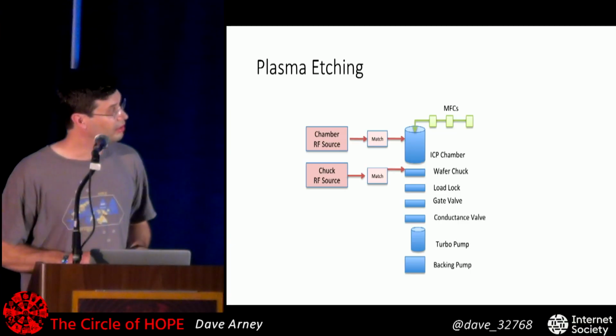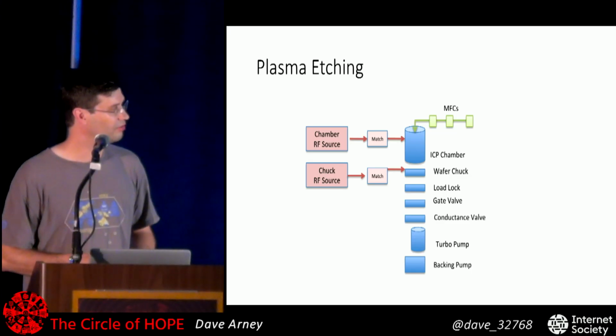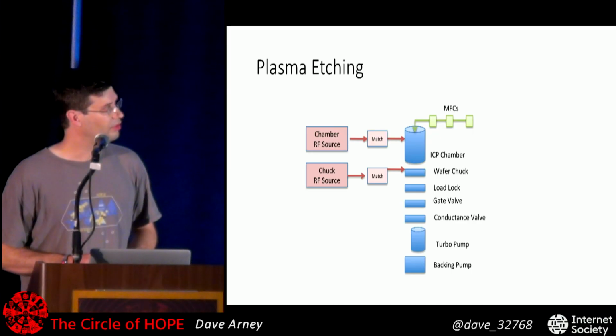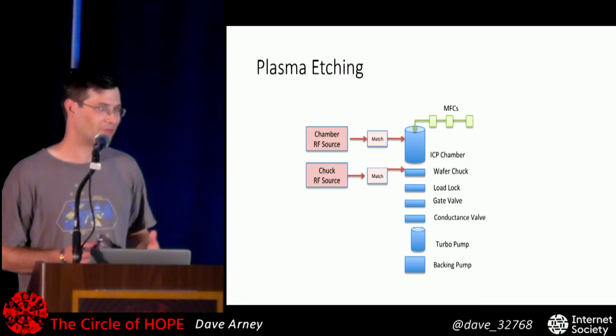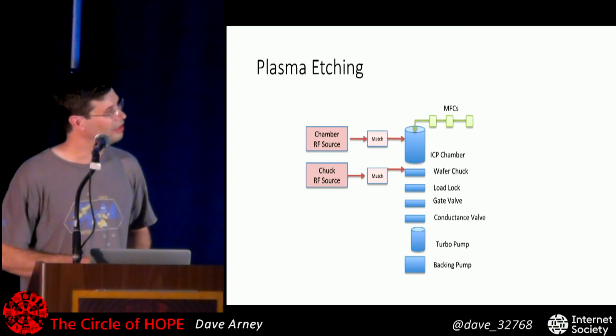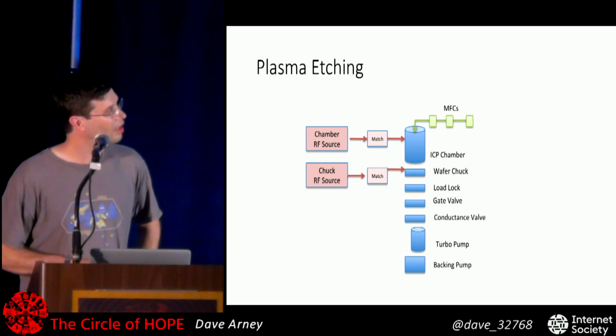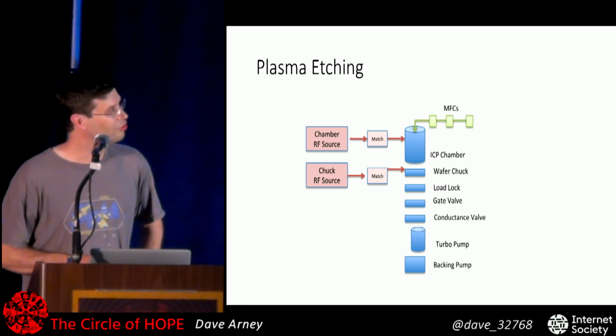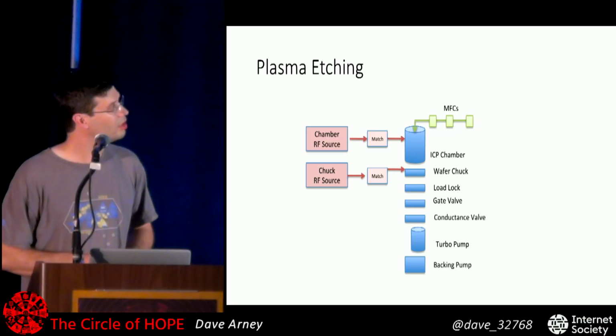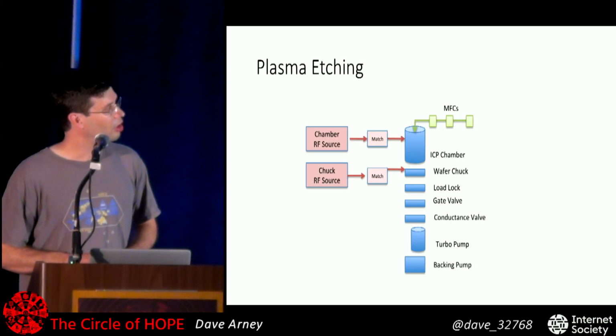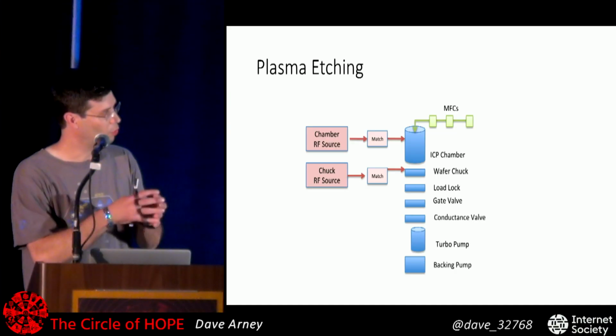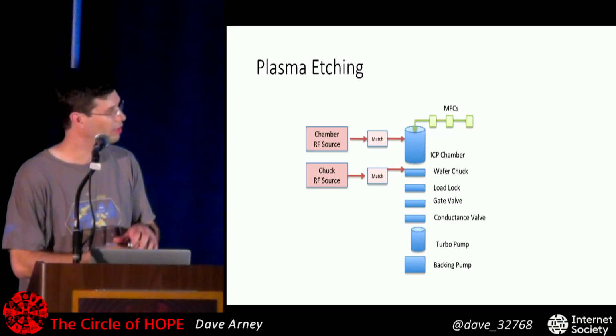To do this, you need a plasma chamber. I'm using an RF inductively coupled plasma, and we'll get into that in a moment. You need an RF source, so this is going to be a few hundred watts to a kilowatt of usually 13.56 megahertz, the ISM band, so you're not interfering with local TV too much. That gets sent into your chamber through a matching network, like an antenna tuner. There's a smaller RF source that connects to the chuck so that the ions that you're creating want to go and hit your chuck, which holds your wafer.